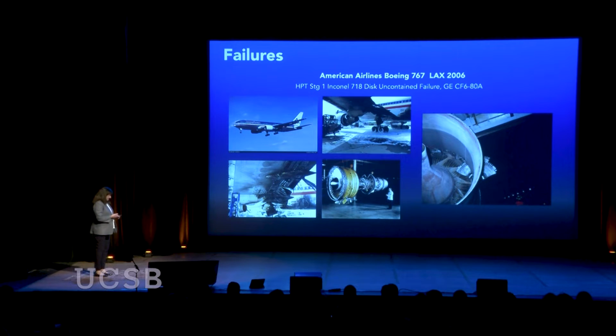So that's pretty amazing. Now, the question, of course, is how could this happen? If this thing fails, that's literally the most dangerous failure you can have in an engine. And so there are detailed investigations, but the bottom line is typically in these situations, there may or may not be some tiny defect, but we develop a crack, and then every time you take off and land, that crack grows a little bit. And eventually it grows long enough to cause that thing to come apart into two pieces. And so what we always want to understand in more detail, and it's what's challenged the development of materials, is understanding in great detail what are the defects and how do they lead to failure.